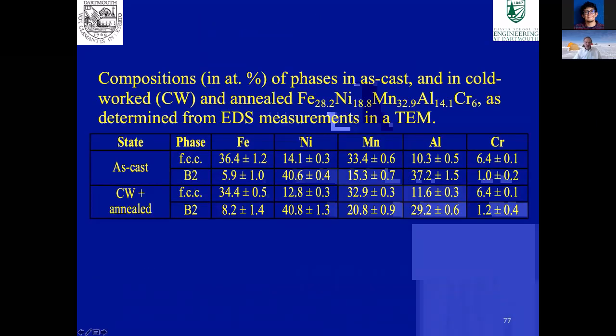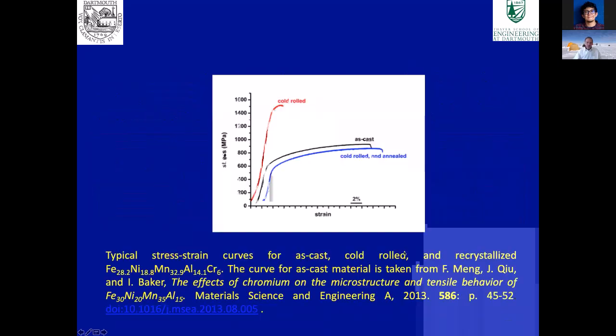And in fact, if we look at the chemistry of those two, so this is the as-cast FCC and B2, and this is the cold worked and annealed, so recrystallized, FCC and B2. There's actually very little difference in the chemistry between the phases before and afterwards. And if you look at the mechanical properties, so this is the stress as a function of strain. So you can see the cold worked material has a much higher yield strength, with very little ductility. And after we cold roll it and anneal it, it's actually very little different from the as-cast material.